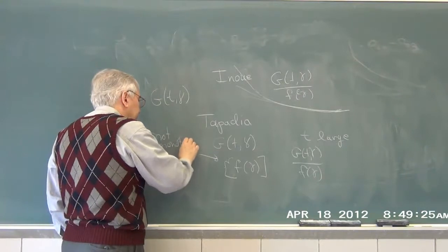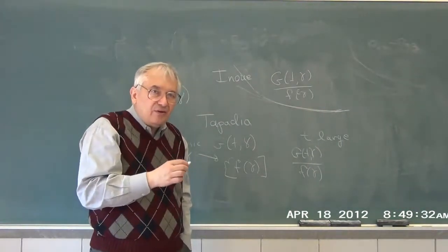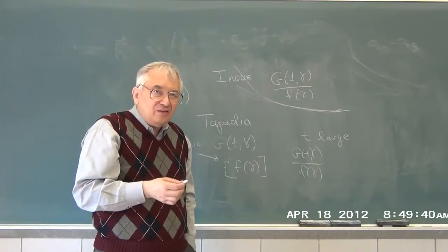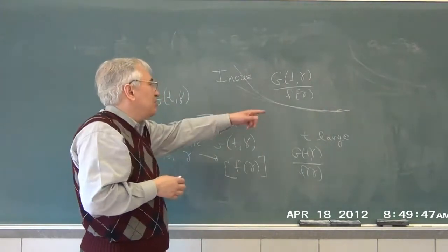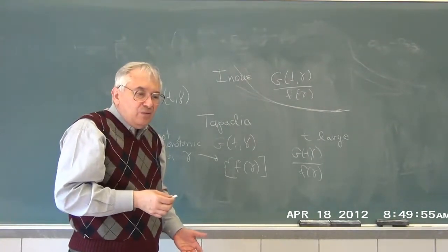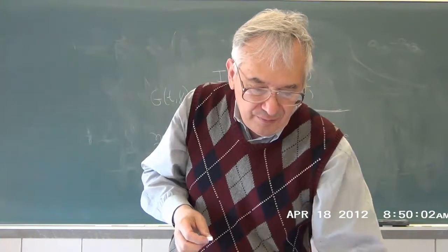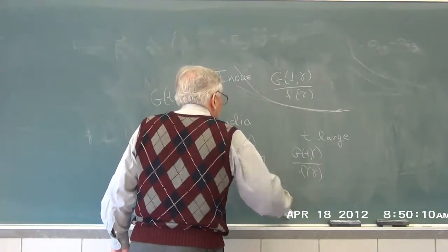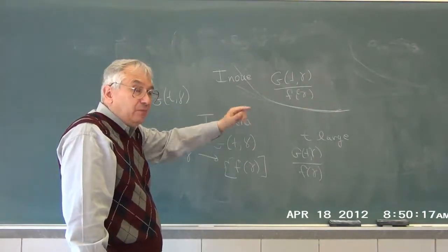monotonic in gamma. That is, yes, you can make the curves agree with each other, but this division factor you have is a bit more complicated than, say, 1 over gamma. And the issue there is that there are a number of models that predict the second behavior, but if you ask what they would say about f of gamma, you would think f of gamma would be monotonic in gamma. And their result is that it is not. Okay. There's a further complexity. This is supposed to be a critical test of some models of polymer dynamics.